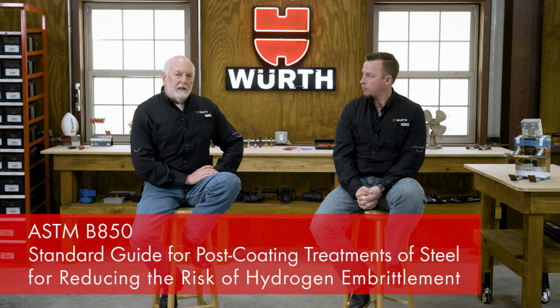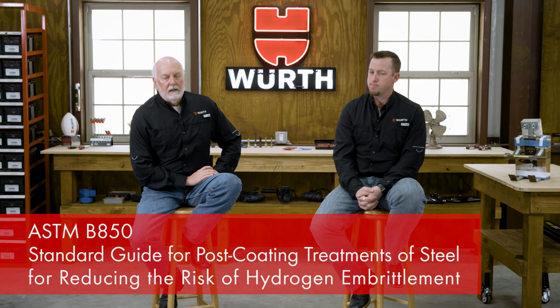So in conclusion, hydrogen embrittlement is a very serious subject. There has been loss of life, there's been severe injury, and there's been failed equipment, all at a high cost. It's a delayed failure. You do not see it in assembly. Based on the electroplating process, you have to be very deeply concerned with any products that are 39 HRC and try to avoid using any electroplating on those types of products. Absolutely. Follow the ASTM B850 guidelines when you are baking. That'll give you exact guidelines of what to do on the bake process.